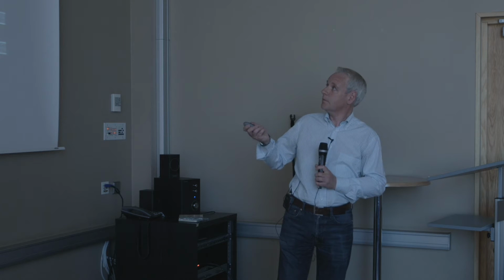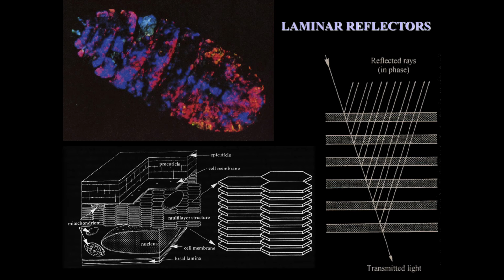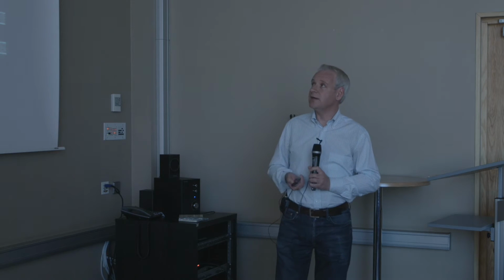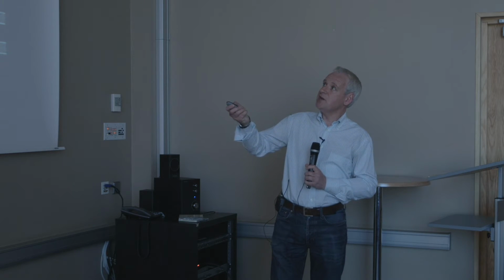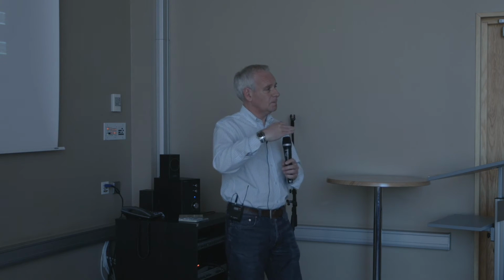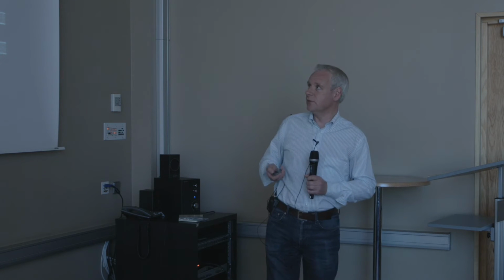Now, when you've got a stack of layers rather than just one, that single one reflected about 5%, from each of those layers, so you've got about 10% reflection. When you've got about 10 layers, you get 100% reflection, total reflection of all the light. So it's an excellent reflector. And here, the change in colour is down to slight variations in the angle. So you've got different wavelengths being reflected constructively from different parts.